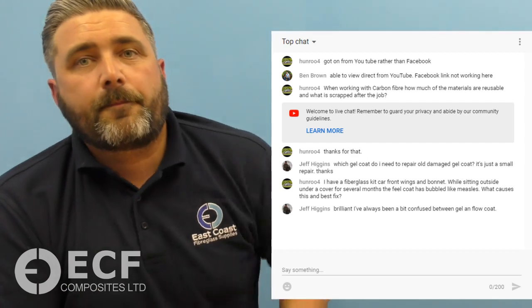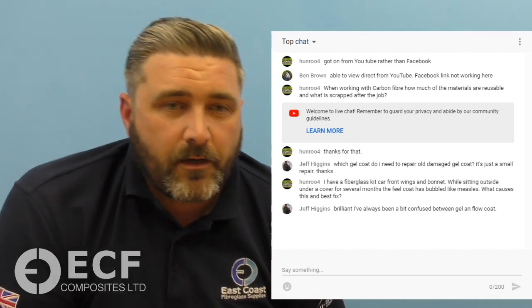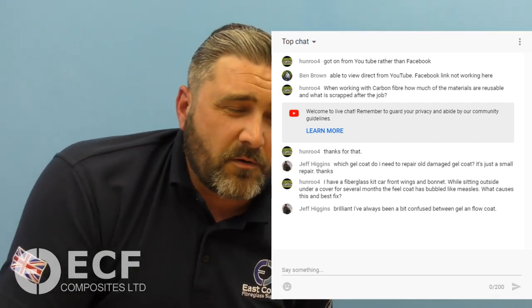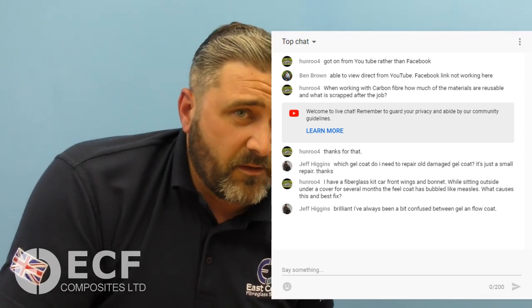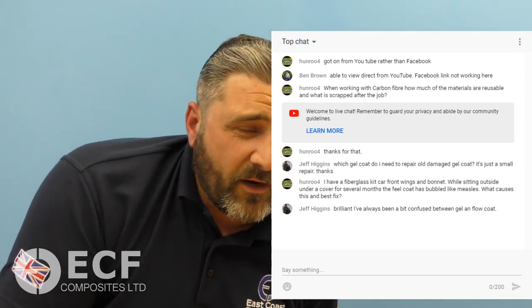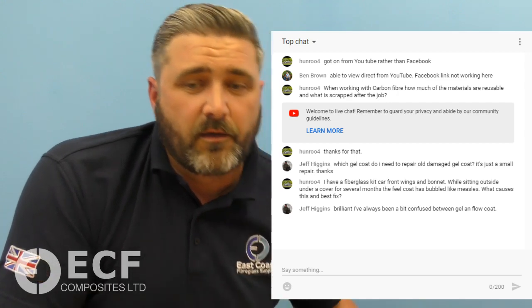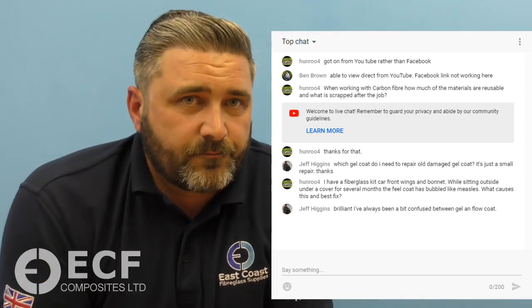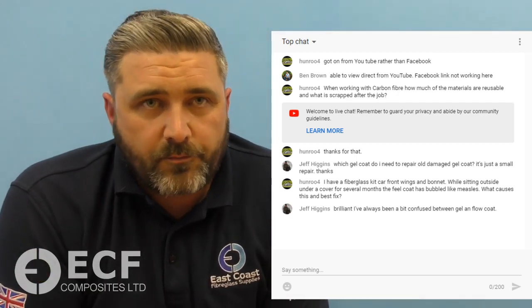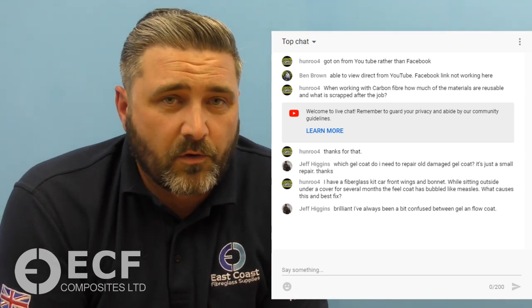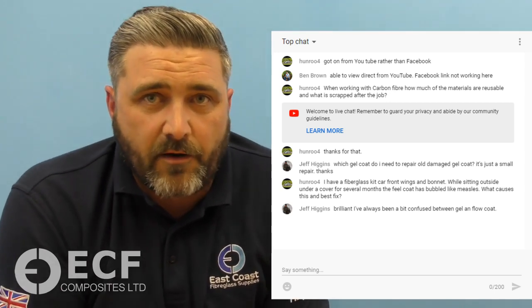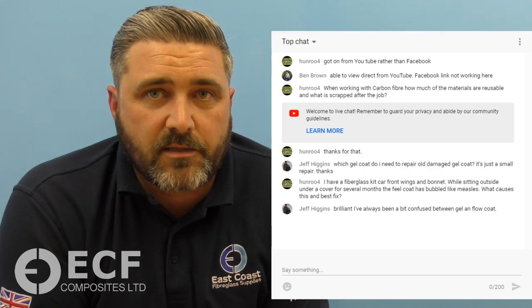So, what's the short answer? Either epoxy or do the polyester. There's not really a quick fix to it. No. Both. And it's caused by water getting into the laminate, probably. Probably, yeah. Unless it's been poorly laid up in the first place and there's been a lot of air in there between the gel coat and the fiberglass.